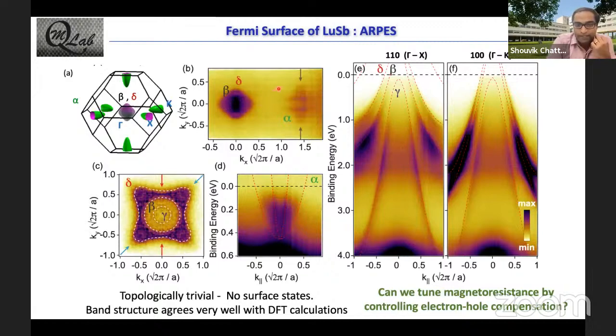And what I'm showing you here in this panel B is the cut through the three-dimensional Brillouin zone through this gamma point, which is at the center. And you can directly see there is a very nice correspondence around the gamma point. You have these two hole-like Fermi surfaces, and at the zone edge you have an electron-like Fermi surface. So you can also take various cuts. If you take a cut along this direction, or you can take a cut along the gamma X direction, you can get an idea about the band dispersions. And what you see here is that they match very well with your density functional theory calculations.